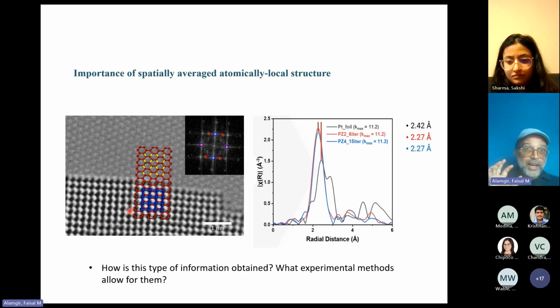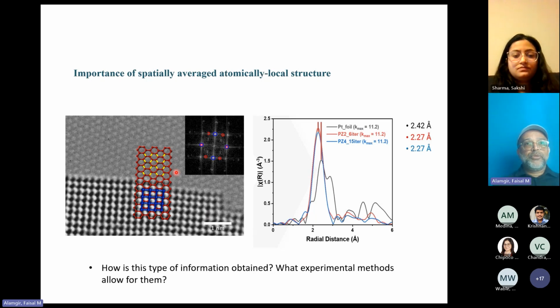However, this type of measurement, by the very fact that it's extremely local, looking at individual atoms, means that we are not necessarily talking about a global average of what's happening, right? And so in order to go from this to a global average, you would need to collect many such images and then do some statistics on that and draw further conclusions about what's actually happening in the entire material. Now, of course, you can get around this by deduction and other analytical approaches, where you can make the argument that we really expect only one type of phenomenon to be happening, and this is it. This is representative. And so you can get around that.